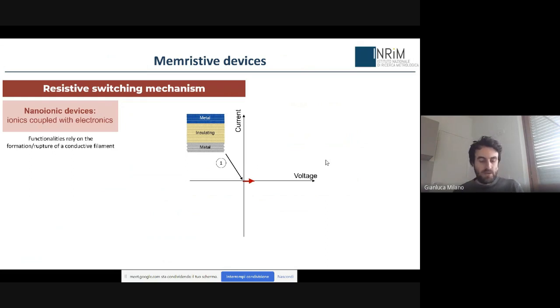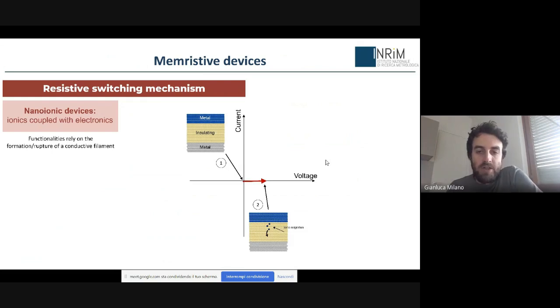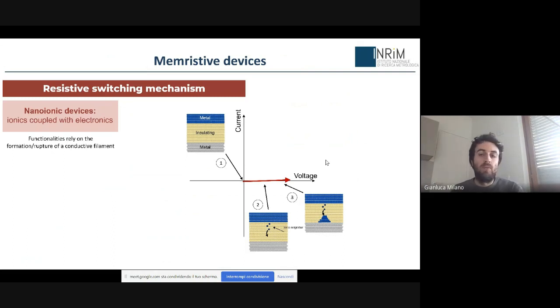A few words about the resistive switching mechanism. These devices are very simple, basically a metal-insulator-metal sandwich. Of course, in the IV plane, initially these are highly resistive because of the insulating nature of the insulator. If we apply a voltage, we can start the dissolution of a few metal atoms to form ions that start to migrate across the insulating layer. If we further increase the voltage, this causes the accumulation of these ions and, with consequent recrystallization, to form atoms again on the opposite electrode.